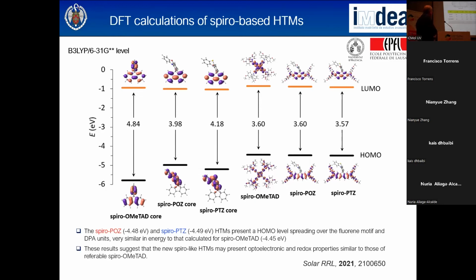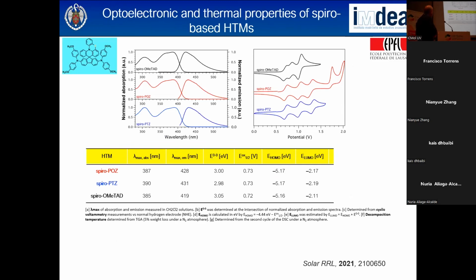This is the absorption and emission spectra for our 2 molecules in comparison with the spiro. I could go into much more detail, but you can see this band corresponds to the electron donor moieties in the molecules, and this one corresponds to the heterocycle moieties. The emission spectra is quite similar. You can see the values are a little bit shifted in our molecules, but with this data you can calculate the optical gap, and the first oxidation potential, which is good to determine the HOMO energy level, and also the LUMO are quite similar.